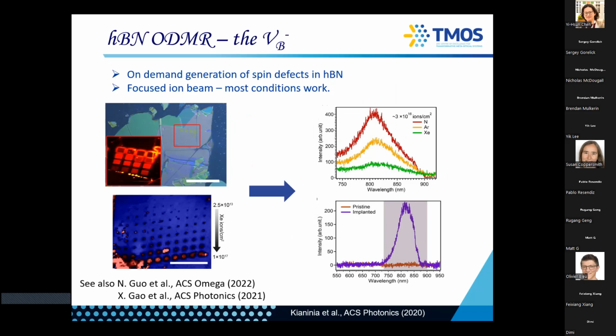And so here we started to chase single emitters because, well, you can create them and they are spin defects. Let's get singles. And so the first attempt didn't work. You see here, the emission intensity basically vanishes to 0, but we could still never record an anti-bunching measurement. Okay, so they're just too dim, meaning that the quantum efficiency is just too low.